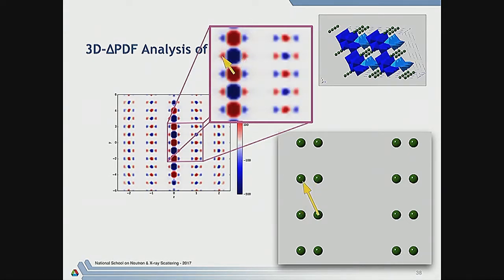But of course, the sodium ion could be on the right-hand rung, and so there could be a probability of it off to the left. So we have these vectors as well, and it represents basically the same thing: we have this diagonal probability, and then of course there are probabilities along the ladders. So these two-rung ladders give rise to three-rung ladders in PDF space, okay? Now, we also, of course, have correlations between ladders. And you can see here, this is exactly one lattice unit. So what that's saying is that if this right-hand rung is occupied by a sodium ion, then this right-hand rung will be occupied, okay?